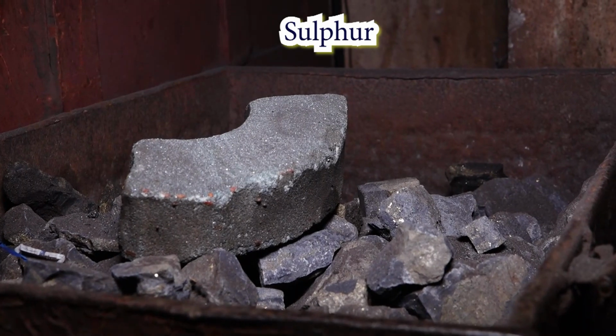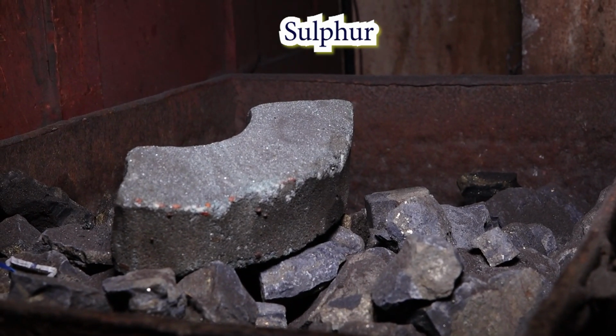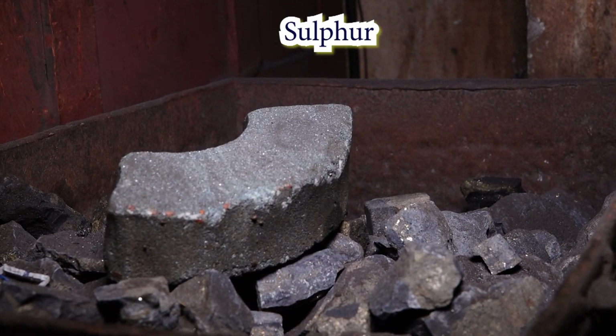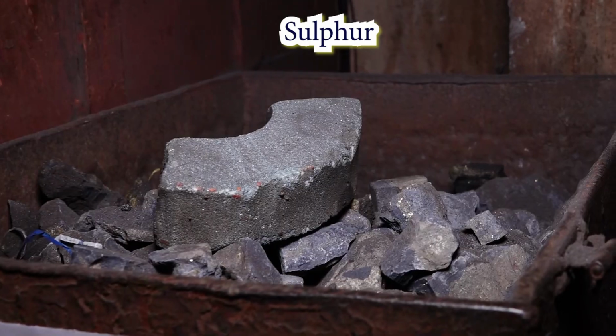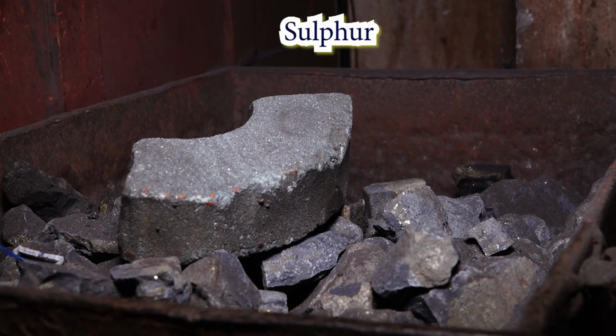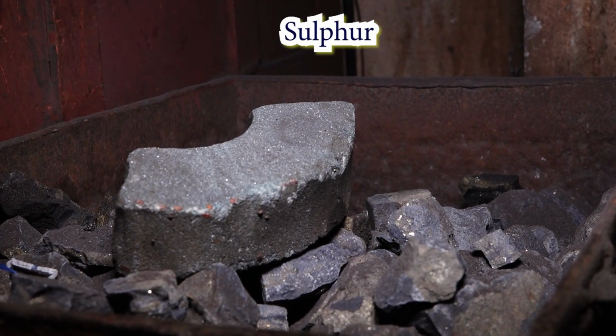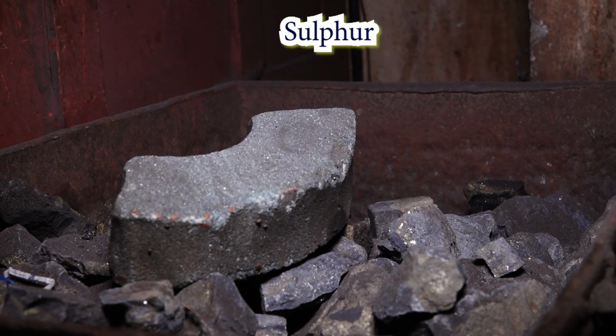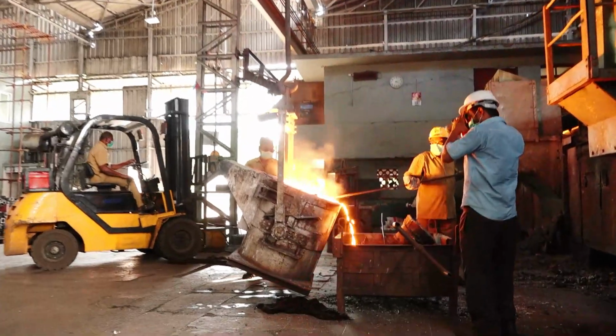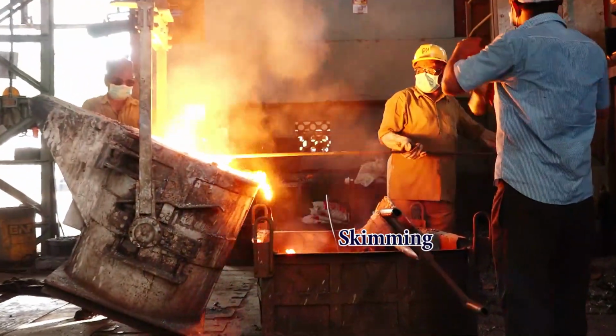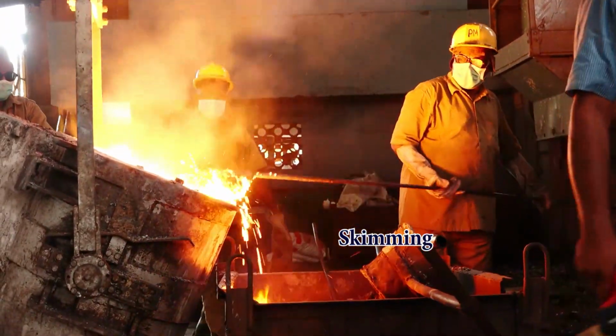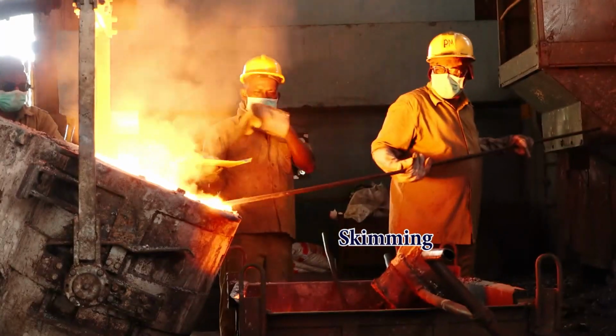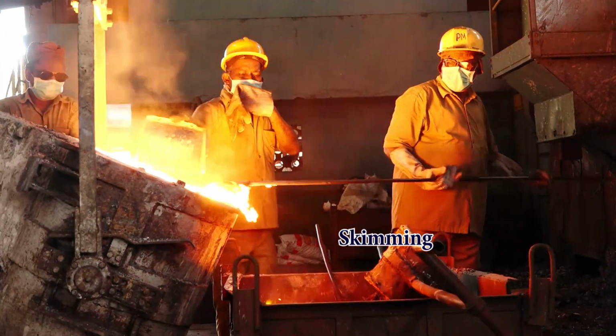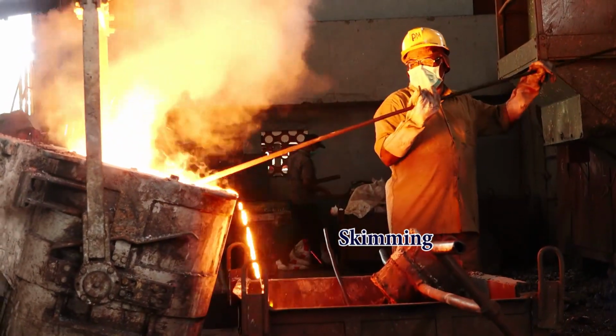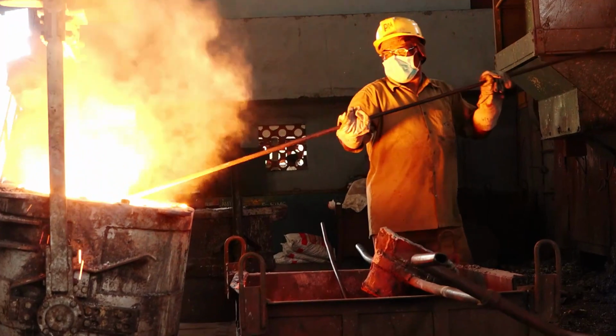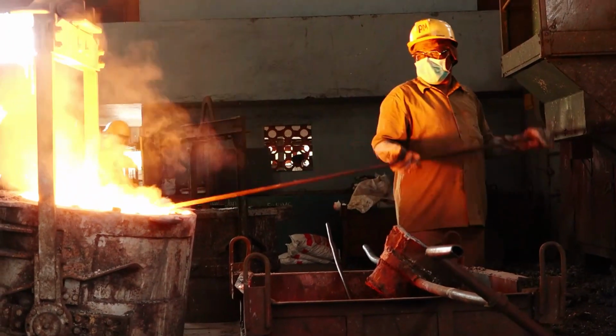Sulfur, largely a contaminant when present, forms iron sulfide, which prevents the formation of graphite and increases hardness. The problem with sulfur is that it makes molten cast iron viscous, which causes defects. To counter the effects of sulfur, manganese is added, because of which the sulfur forms into manganese sulfide instead of iron sulfide. The manganese sulfide is lighter than the melt, so it tends to float out of the melt and into the slag. Very low sulfur content also results in low nodule counts, poor graphite shape, increased shrinkage, poor machinability and brittleness.